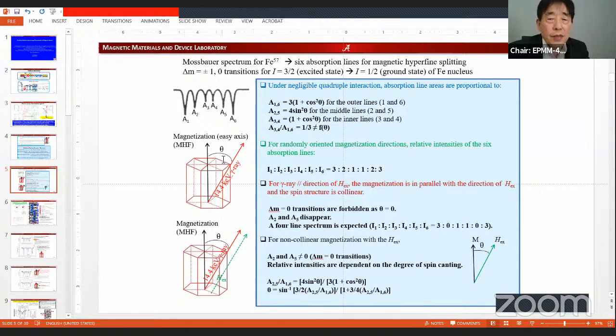So once you change this gamma ray direction toward your sample, you can control the area intensities A1, A2, A3, and then you can predict the angle between this c-axis and the gamma ray direction. And likewise, you can apply this gamma ray in parallel with the applied field here, and then apply the field. In this case, you have a different A1 through A6 ratio.